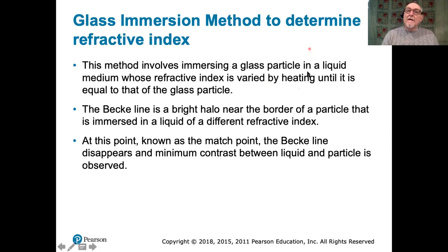Now, what about the refractive index? This is the standard method for determining refractive index. Again, we're going to immerse our piece of glass in a liquid. If the glass is not already very small, we can take small fragments of it. We're going to do this under a microscope, and we're going to drop the glass fragments into a liquid.